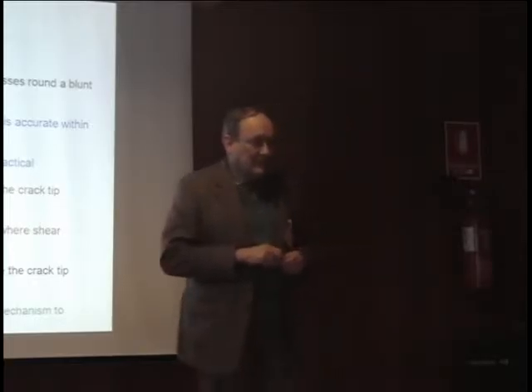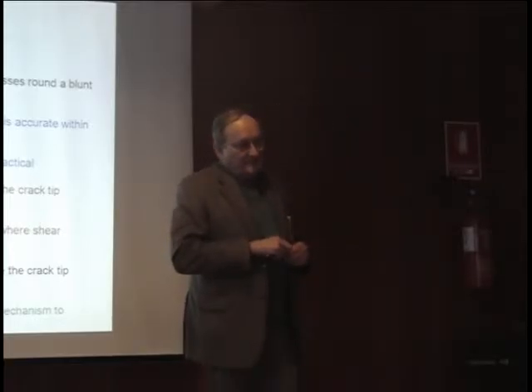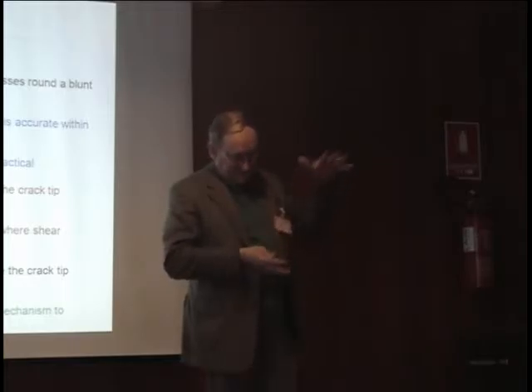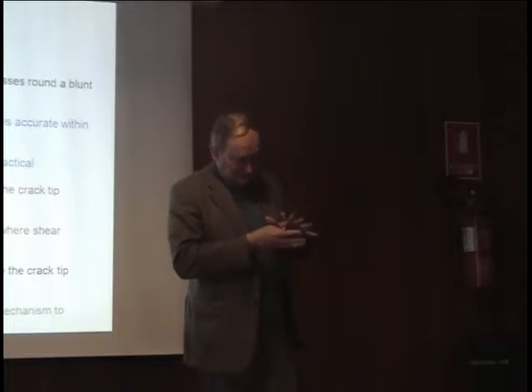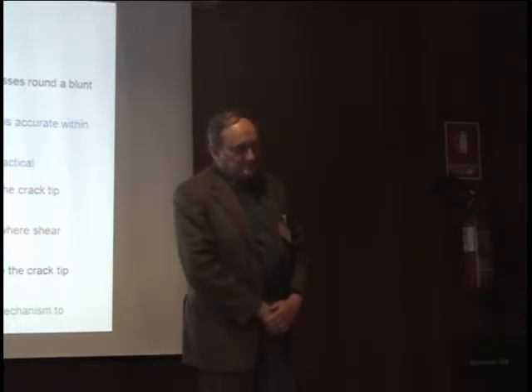Yeah. So you have something like a Brazilian disc test. Actually, if you apply the stress like this, you apply some mode 1 to the crack tip. You would get a small mode 1 in tension, equal to the T-stress effectively, that you're applying parallel to the crack. Compressive stress, that's right. If you crack it like this and you apply this compressive stress, you apply actually the mode 1 across the crack there. So actually you have a mode 1.